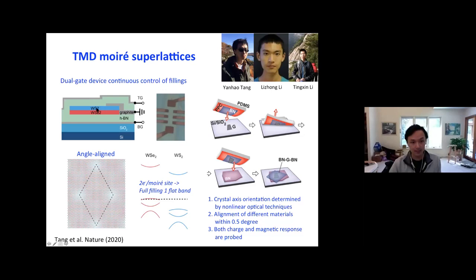And this is an example of WS2 on WSe2 sandwiched between two gates made of boron nitride crystals. They are dielectric materials, and then a gate by graphite, top and bottom gate, with which you can apply an electric field as well as change the doping level in this heterobilayer. The heterobilayer can be contacted by graphite electrodes or by platinum electrodes if we want to do some transport measurements. And the structure is like this, as I mentioned.